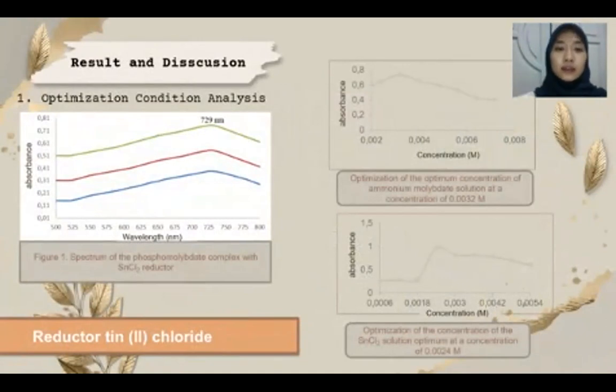And next, results and discussion. The first, optimization of analysis conditions. For the optimization of analytical conditions on tin(II) chloride, the maximum wavelength was determined by measuring the absorption of the heteropolyphosphomolybdate complex compound in the visible area in the range of 500 until 800 nanometers. The result was a wavelength of 729 nanometers.